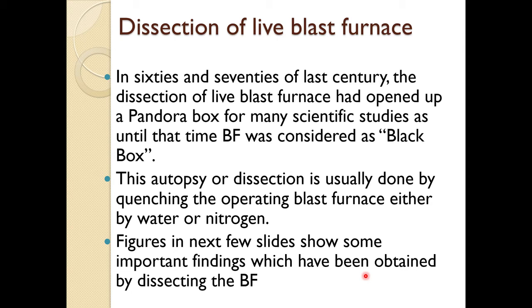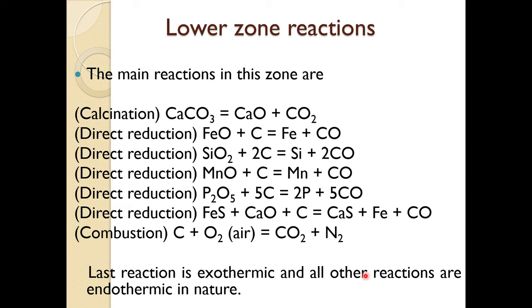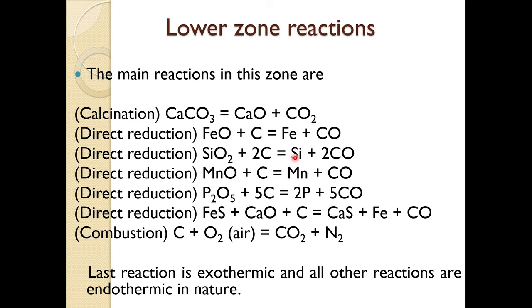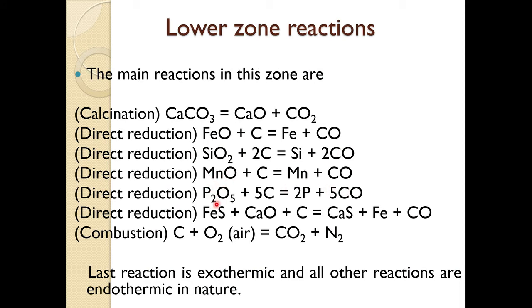The silicon pickup reaction is very important in the blast furnace. Less silicon in the hot metal is desired, otherwise desiliconization — an additional and expensive operation — is required after the metal is tapped, increasing steel production costs. Phosphorus and sulfur and how they affect the chemistry of liquid iron and slag will be discussed in detail at a later stage.